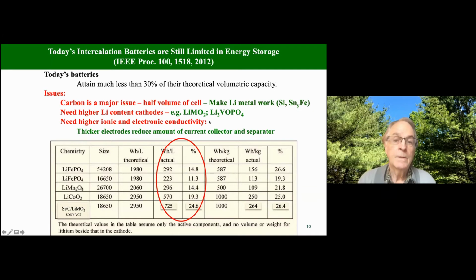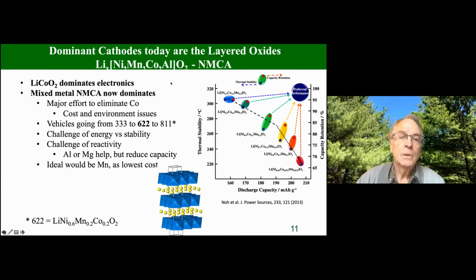The other issue we need to address if we want to increase the energy density is to get rid of more of the dead weight. We can do this first by just making thicker electrodes, so we can cut down the amount of current collector and separator. So if we double the thickness, we can cut out half the current collectors and separators. So let me look at the layered oxides, and I'll build a little bit and not duplicate too much of what Jeff has said. For electronics, lithium cobalt oxide still dominates. For the other materials, the mixed metal NMCA now dominate.